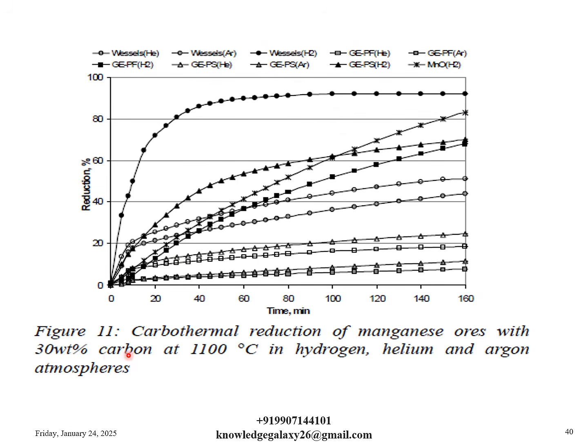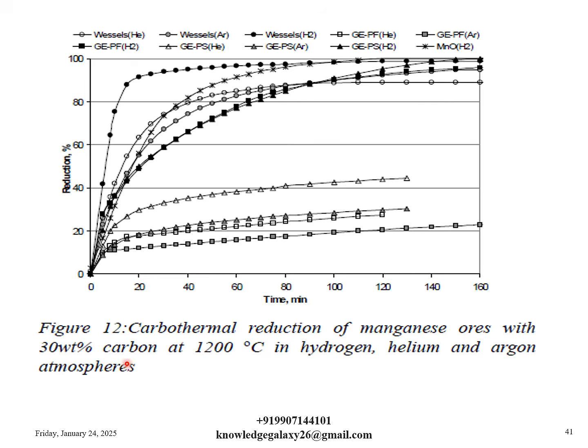And this is figure 11, which shows the carbothermal reduction of manganese ores with 30 weight percent carbon at 1100 degrees Celsius in hydrogen, helium and argon atmospheres. This is figure number 12, which shows carbothermal reduction of manganese ores with 30 weight percent carbon at 1200 degrees Celsius in hydrogen, helium and argon atmospheres.